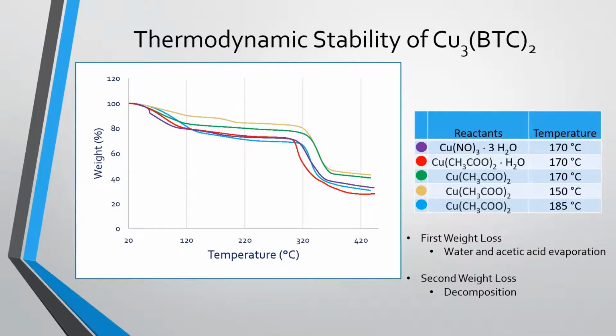Our second weight loss occurred around 300 degrees, which was likely from the decomposition of our copper BTC. This is compared to reference standards, and they also decomposed around 300 degrees.